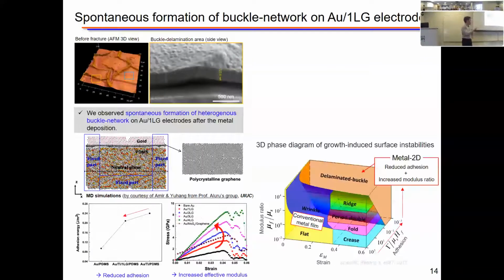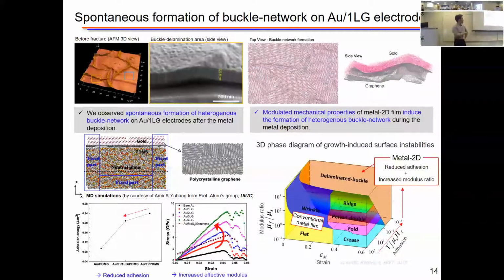So we looked to unveil the mechanism with the support of molecular dynamic simulation by the collaborators of Professor Aluru from U of I. We revealed that after the metal deposition, there's a formation of a heterogeneous buckle network in the film. That's because by inserting 2D material, we're changing the film property. You're increasing the modulus, so referring to the phase diagram of the formation of structure and surface instability, this delamination buckle is what we're interested in.